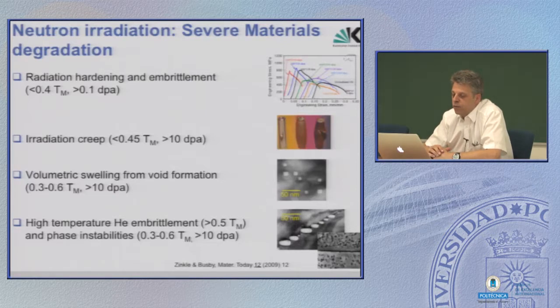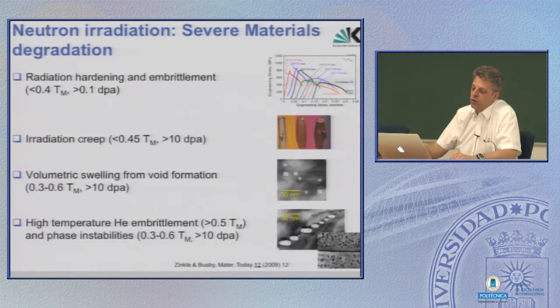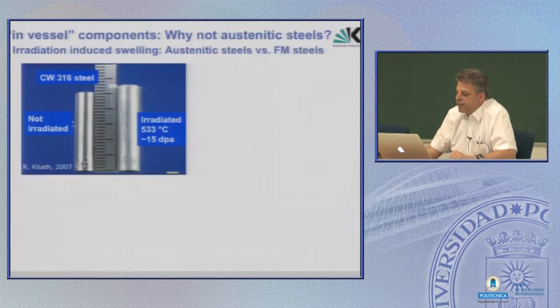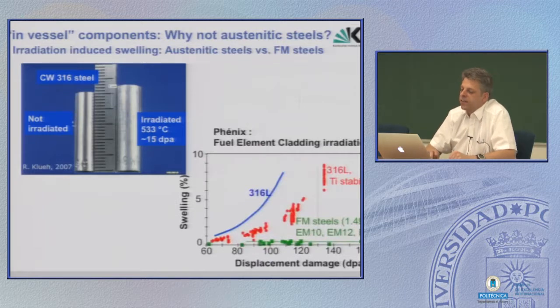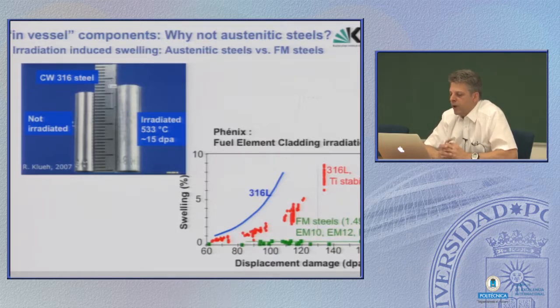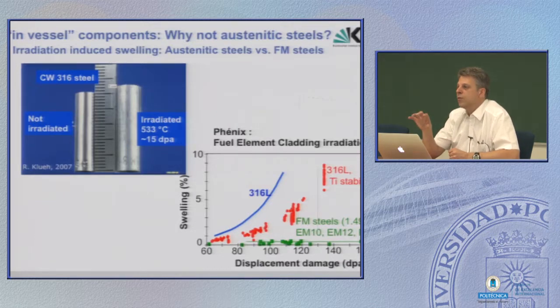All have specific ranges of temperatures and also dpa, but for future fusion power plants the helium embrittlement is probably the severest one. Another reason we have seen already yesterday why 316 steels should not be used for higher irradiation doses is the swelling. And also from yesterday, you see that the green line, the ferritic martensitic steels, doesn't show such high swelling rates. So in principle, even at 150 dpa and higher, the swelling would be within an acceptable range. And that's why for all further fusion concepts beyond ITER, these 9% chromium steels are, let's say, the backbone.